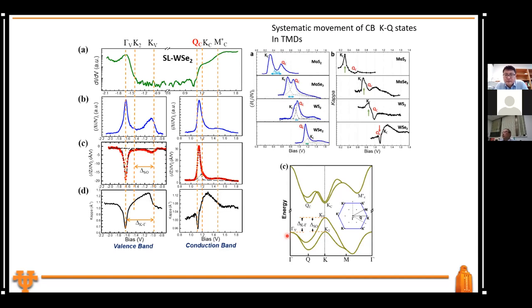A similar behavior can be used to describe the behavior at the conduction band. In the conduction band, we can determine the threshold at the K point and another threshold at the Q point. And then you can see the evolution of this K-Q transition as a function of these four different transition metal dichalcogenides. And one very interesting phenomenon is, it seems that in WSe2 this Q point and K point are nearly degenerate. We even argue that the Q point may be slightly below the K point.